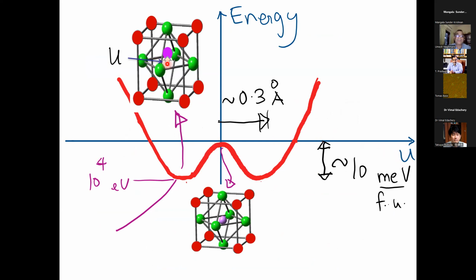U is the displacement of this titanium atom in barium titanate, for instance, from its centrosymmetric position. And that centrosymmetric position corresponds to this point, U equal to 0. That's the cubic perovskite structure. And as you distort the titanium atom, off-center it, the energy of the lattice reduces. This energy, by the way, is calculated within a first principles, density functional theoretical framework, and you get lowering of energy like this, and it settles in one energy well. Of course, if you flip the direction of off-centering, you will get another energy well here corresponding to negative dipole moment. And likewise, in fact, there are many other symmetry equivalent energy wells.